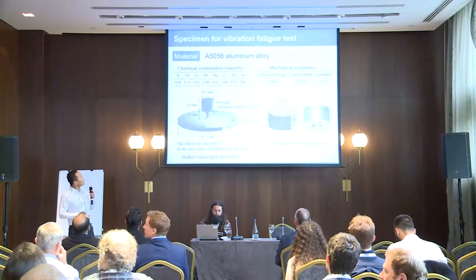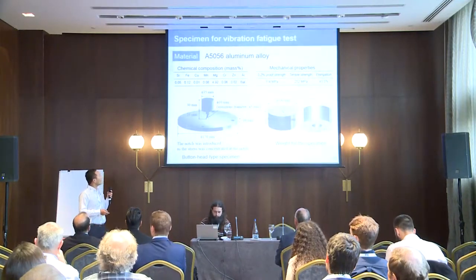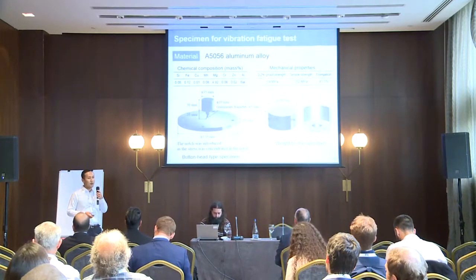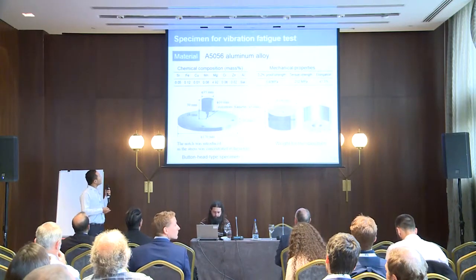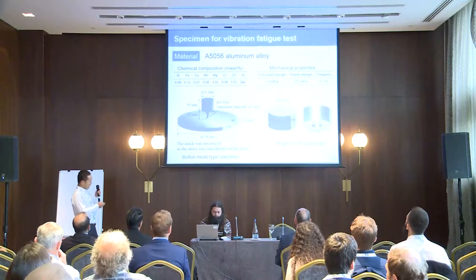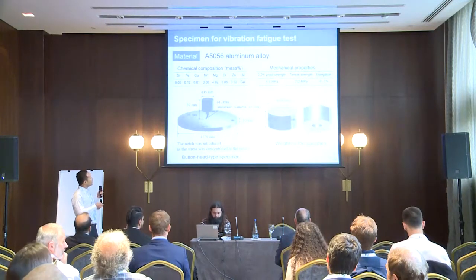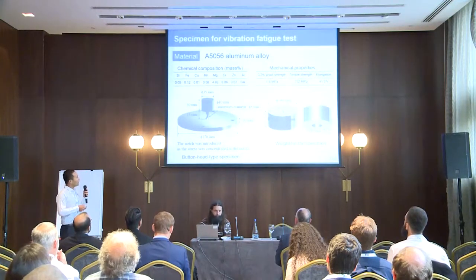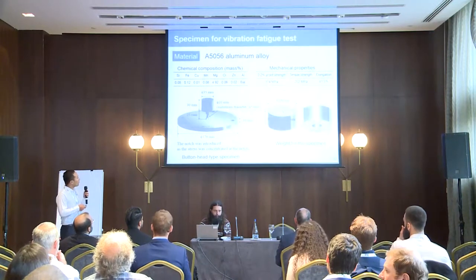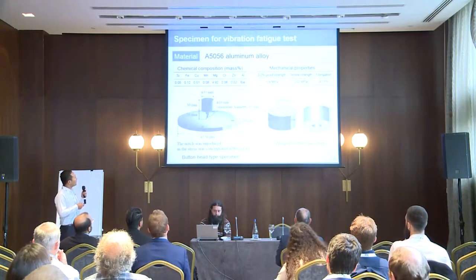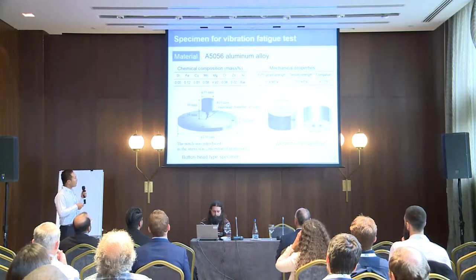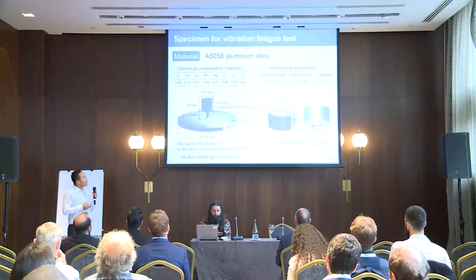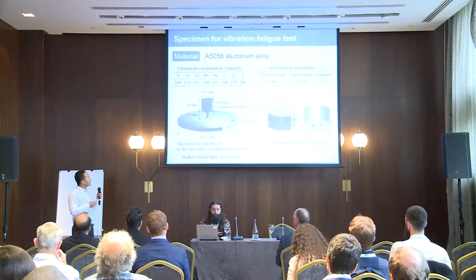This slide shows the specimen for the vibration fatigue test. We selected the A5056 aluminum alloy as testing material, and the chemical composition and mechanical properties are listed in these tables. This figure shows the button-head type specimen and weight for the specimen. We employed the button-head type specimen and introduced a notch so that stress was concentrated at the notch.